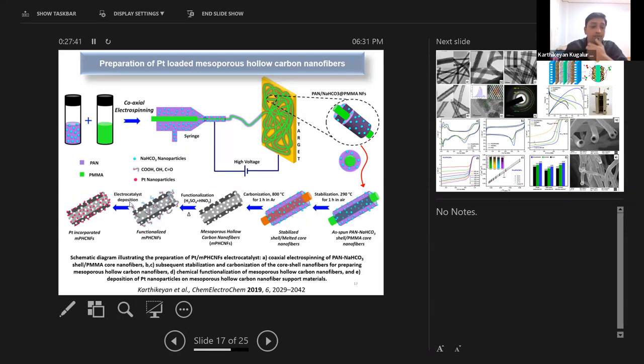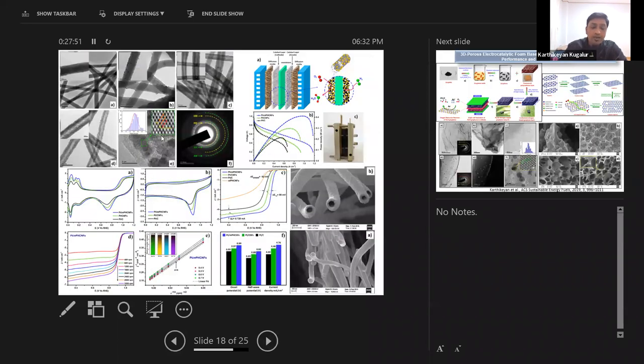Then we do the functionalization process for the deposition of the electrocatalyst. And finally, the platinum will be decorated on the mesoporous hollow carbon nanofibers. Similarly, we have characterized them using several techniques. So this is the transmission electron microscopy image where you can see the hollow structure inside the nanofibers. And the platinum nanoparticles are also deposited onto the mesoporous hollow carbon nanofibers. So this is the field emission scanning electron microscope image where you can see the hollow structure of the nanofibers. Finally, we have used the cyclic voltammetry technique and linear sweep voltammetry analysis for understanding the performance of the material. So we have identified that this gives maximum performance when compared to the commercial benchmark electrocatalyst.